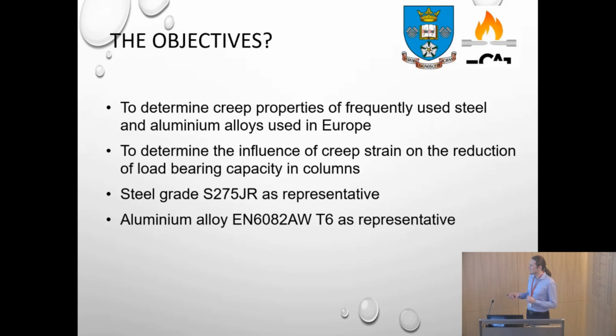These two alloys are similar in that aluminium of this grade has a proof stress which is equivalent to the steel grade's yield strength of around 275 megapascals. So it's a good alloy for comparison in terms of resistance.